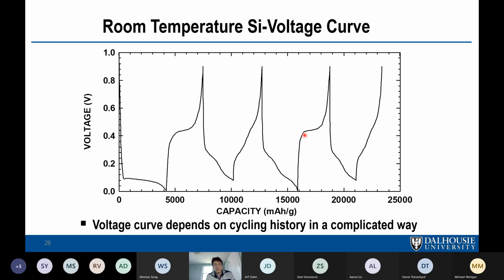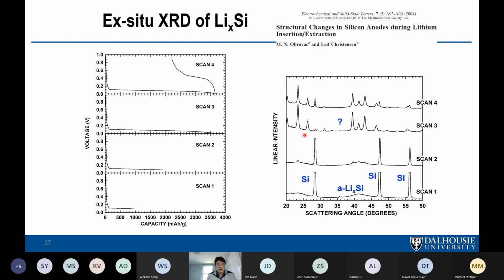So this was quite a challenge to figure out what was going on here. And this is an early paper again. You can see the voltage curve looks pretty crappy. This is improving the cycling of silicon just by adding carbon black. But it was good enough to figure out pretty much what was going on.